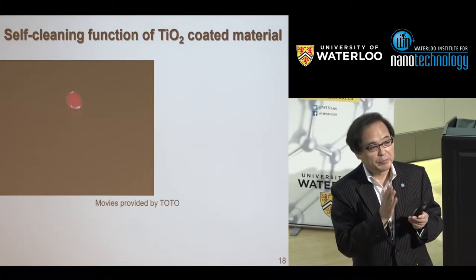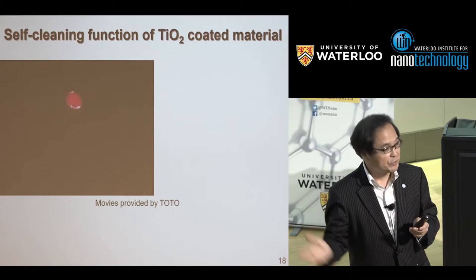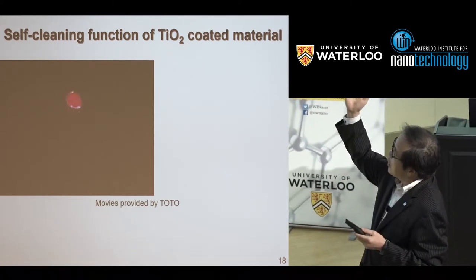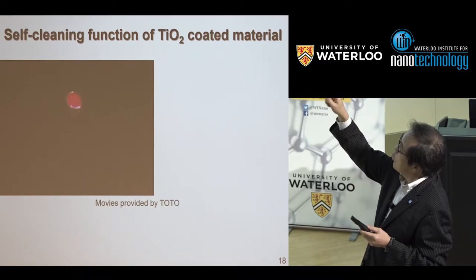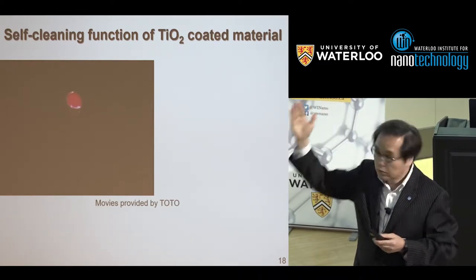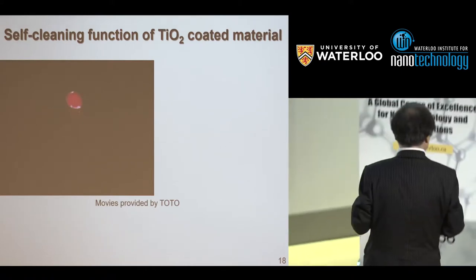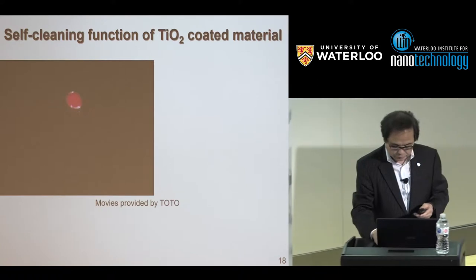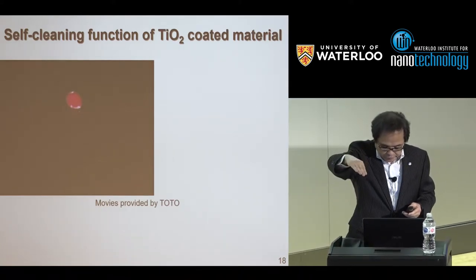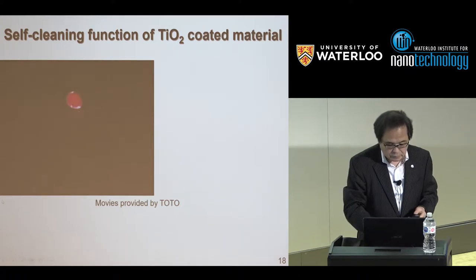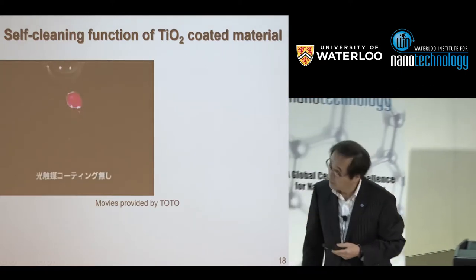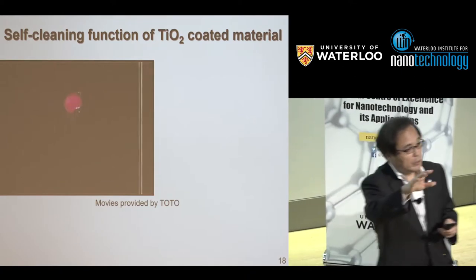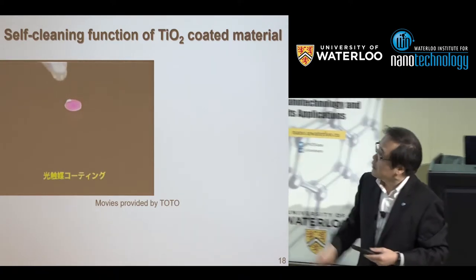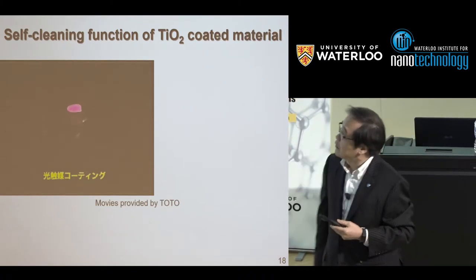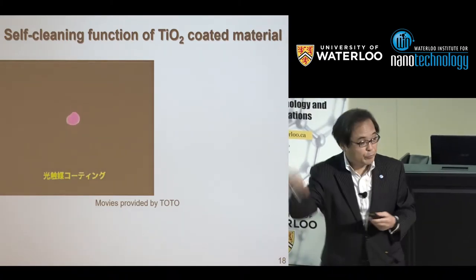In addition to such a mechanism, more important, more interesting is applications. This is a photo of an oil droplet colored red on the substrate. Initially, this is a conventional substrate without titanium dioxide, and this plate is slightly tilted. And water is coming from the top. This is a conventional substrate. Oil sticks on the surface. But when we have the titanium dioxide coated one, then you can see oil is moving.